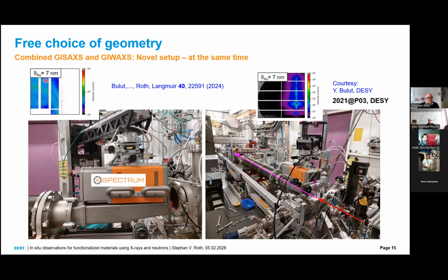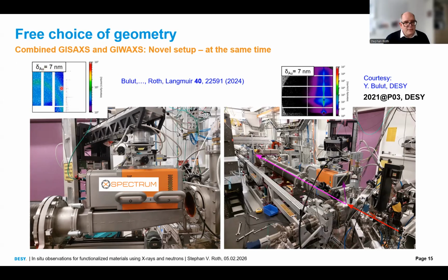Yeah, you see here, this is a typical scattering pattern of the metal on a polymer film. You see here these powder rings from the different reflections of the metal clusters, while here you see the metal layer growth, the nanostructure of the nanocluster layer. And very important is we do this in situ and at the same time. So we are depositing and measuring at the same time both the crystalline reflections and the small angle part.